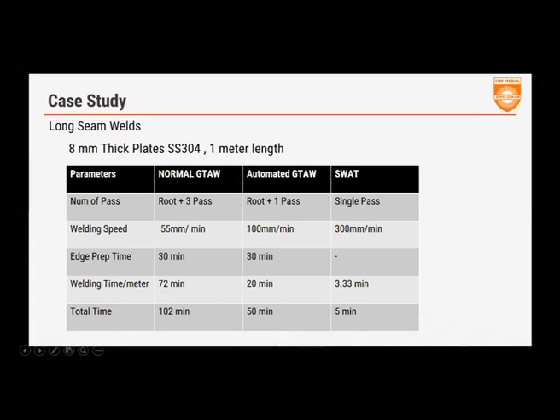Normal manual speeds are about 55 millimeters a minute. This would be 4 meters of weld because there will be 4 passes. You are looking at something like 72 minutes of weld time per meter. And that total time means 102 minutes to complete the job with edge preparation and welding.